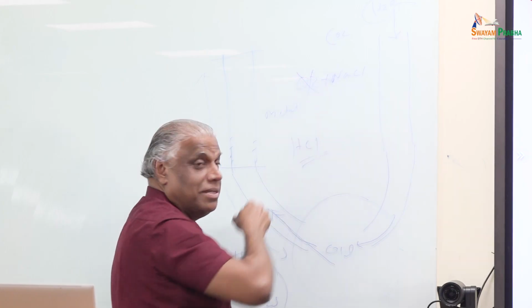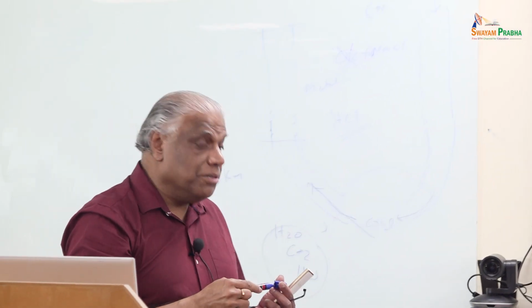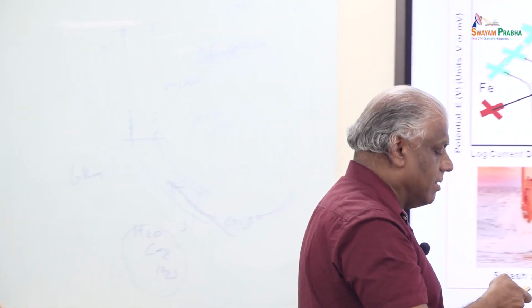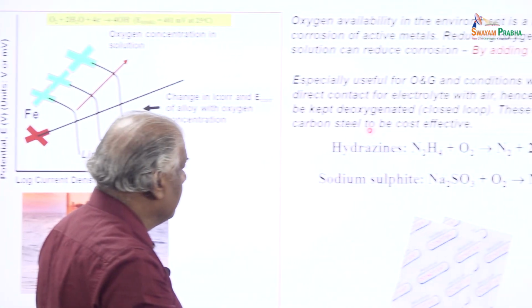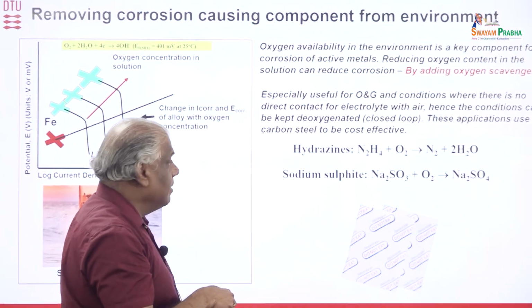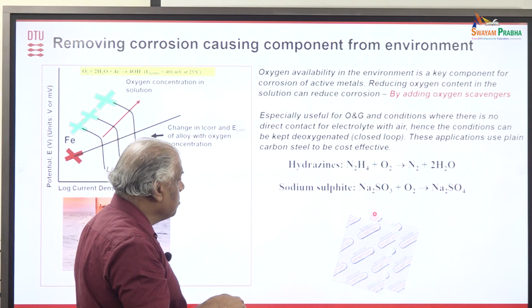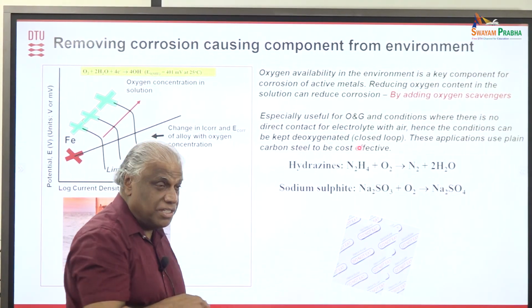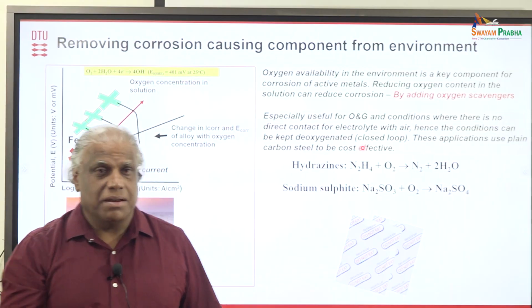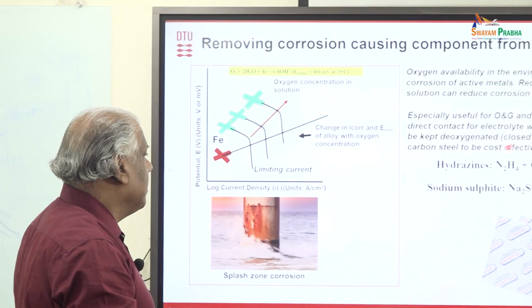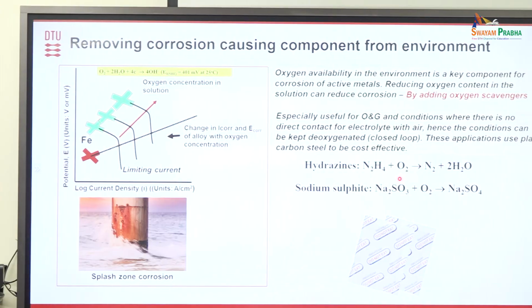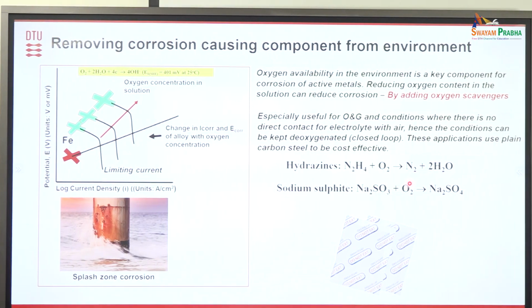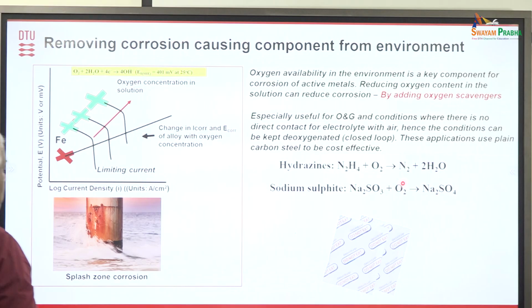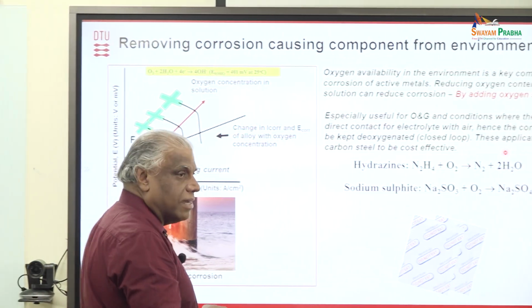This they cannot avoid, but at least this they can remove. And this is what they do to reduce the corrosion problem. So that's where this is important. That is, if you can add some kind of scavengers which can take this oxygen, then it is a good thing. For example, people use sodium sulfite and hydrazine, which is not that much problematic for the environment, and still they use that, and that will take the oxygen, and this forms nitrogen and H2O, and that way the oxygen is removed from the system.